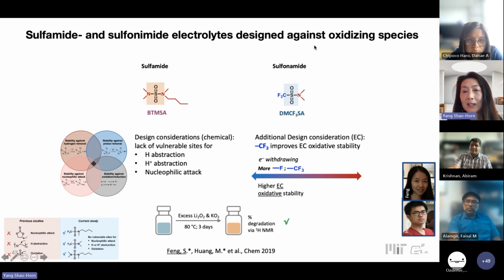And we find, for example, the sulfonamide-based electrolyte has fewer hydrogens relative to our conventional carbonate electrolyte. With these hydrogens, they're much more resistant to oxidative dehydrogenation. And these molecules can essentially survive the test of excess peroxide, superoxide at 80 degrees C for 3 days without degradation, using NMR examination.